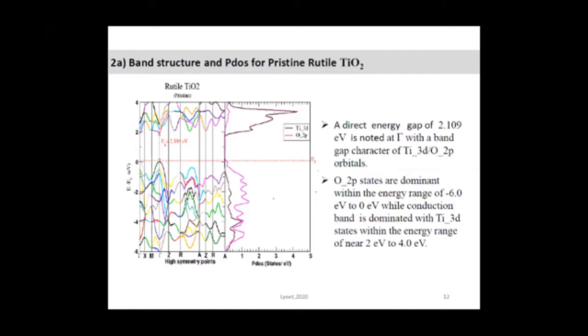These band gaps are underestimated, as expected in DFT, because we are working at ground state. The band gap character for the pristine material: titanium 3d is dominant on the conduction band, and oxygen 2p is dominant on the valence band. Oxygen valence, titanium conduction. That's what you can see.